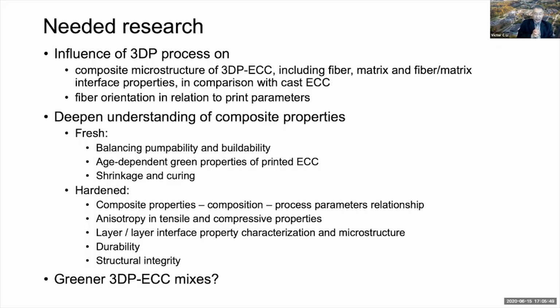And the anisotropic properties, both for tension and for compression, have not received enough attention. This is an area which is also important, particularly from the perspective of structural behavior and the ability to predict and simulate structural response under load. The interface behavior, I already mentioned, is very important. That could become a potential weakness, and therefore we must pay attention to both properly understanding the microstructure of the material near and at the interface, as well as how to characterize and control that behavior.